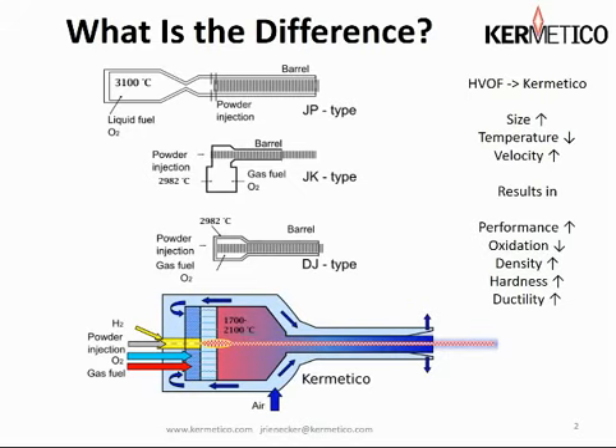First up we have the JP type gun. It has a combustion chamber. Liquid fuel and oxygen is added and it burns, combustion every which way. It gets choked down through a narrow point here and then off into the nozzle. Powder is injected radially from two sides. I suspect the idea here is that the two impinging powder streams will cause the powder to be locked up in the center of the nozzle and head downstream with the gases that are accelerating it and heating it from this point. Interestingly, as the gases expand, they're cooling, but the temperature is so high to begin with, 3100°C, that it really doesn't matter.